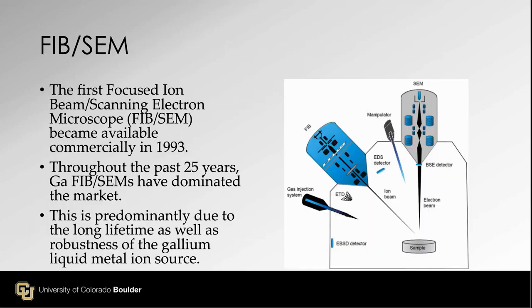Okay, finally we are here: FIB-SEM. The first focused ion beam scanning electron microscope instrument became available commercially in 1993. It has two columns: typically the SEM column is top down, straight down, and the FIB ion source is connected sideways. Throughout the past 25 years, the gallium FIB-SEM has been the dominant instrument, with the gallium ion beam. This is due to the long lifetime as well as the robustness of the gallium liquid metal ion source.